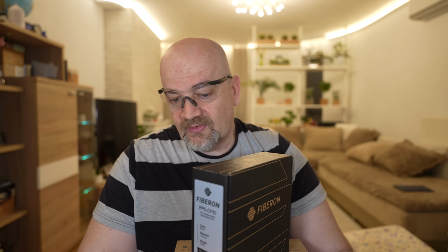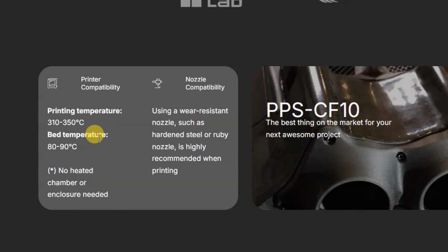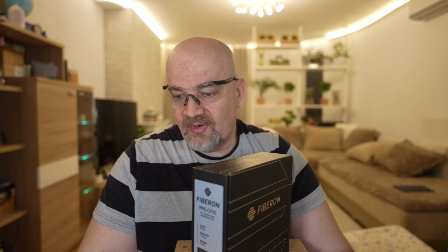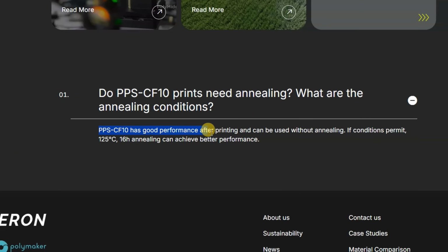Now the print temperatures. Nozzle between 310 and 350 degrees Celsius, so quite high temperatures we need here. Bed between 80 and 90 degrees Celsius, and no heated chamber required. Very resistant nozzle, of course, because of those carbon fibers. And PPS-CF10 can be used even without annealing according to the website.